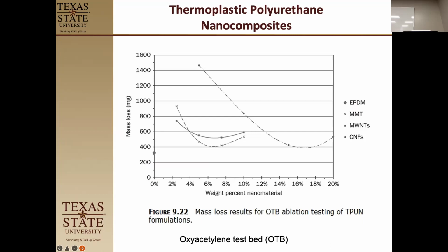Okay. Now, in the case of the carbon nanofibers, we have a huge loss to start off with, and putting more of it in kind of levels it out a bit, but it still doesn't get close to where we saw there. And notice these were only filled 2.5 to 10%, but the carbon nanofibers were all the way up to 20%. So that's why their curve is extended at 15.